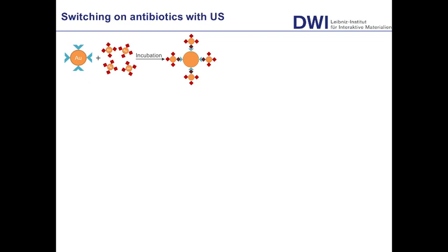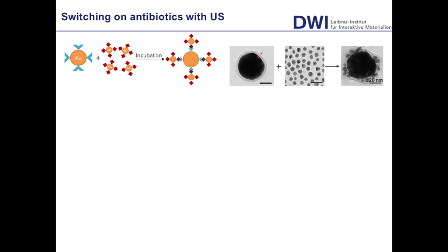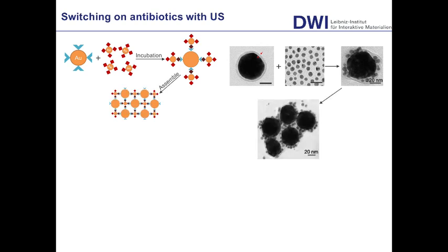So we have synthesized the two particles. Again, as mentioned before, the synthetic peptides and the natural peptide drug play very important roles. Here you see the big and the small particles. You see that the peptide motif on the big particles is able to assemble the small particles around it. Once you let the solution stand for longer, then you form particle networks that are induced by the recognition of the antibiotic with the peptide sequence.